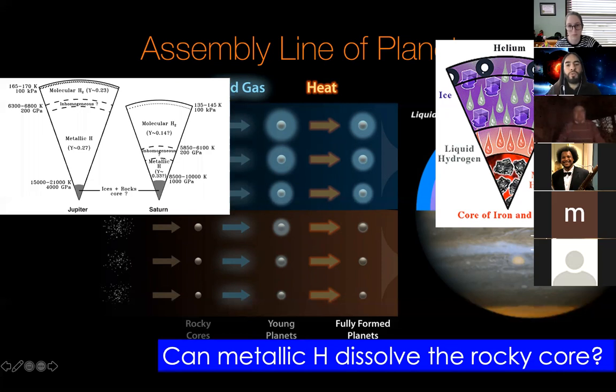So we have to consider that the conditions in Jupiter's core are around 4,000 gigapascals, which is around 40 million times the atmospheric pressure. And temperatures are around 15,000 or 20,000 Kelvin there. So there are no experiments, no chemical models that allow us to predict how this interaction will take place.